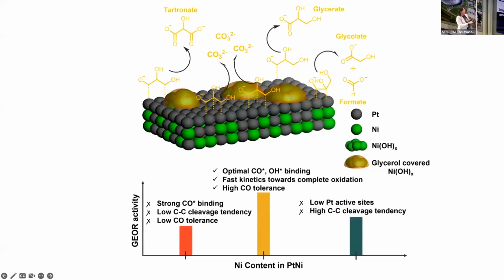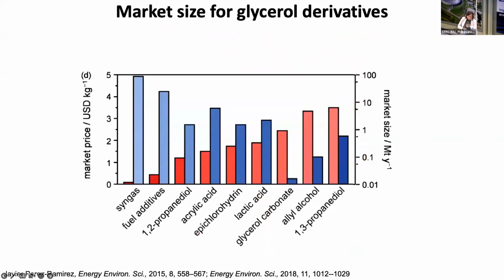So pretty much in the picture, it means that at low potential you have low CO binding energy, and as you increase it you have high CO binding, and this seems to be optimal. And just very briefly, and I can't give details about this, we made this mixture of acids from glycerol. We understood the mechanism was interesting, but then we were wondering, should we actually target something? What do we want to make from glycerol that is useful?